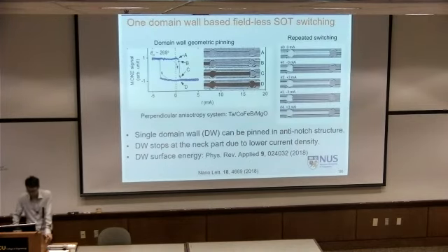Sure. So the thermal effect doesn't really depend on the current direction, because your thermal effect in the z direction will be the same, either you apply current in this way or this way. So you can always subtract your thermal effect by doing this current-direction-dependent measurement, and the final output should be purely a current-direction-dependent effect. So you can always subtract those. And in fact, in our measurement, we found the thermal effect is negligible in terms of switching contribution.